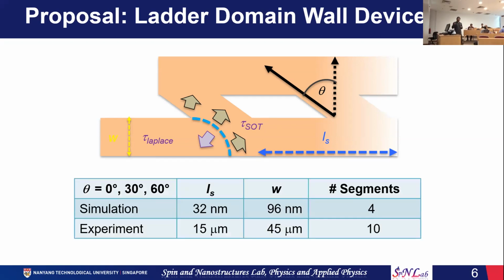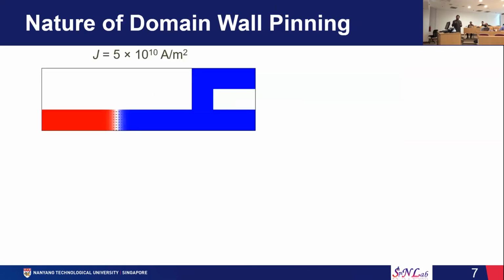So we basically studied the domain-wall dynamics in micromagnetic simulation, and in experiment as well. To understand this pinning behavior in depth, we need to explore this video. You can see that initially the domain wall performs such oscillation, and finally it gets pinned at a particular position at this junction for a certain current density, 5 × 10^10 ampere per square meter.